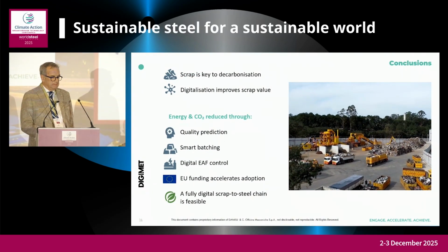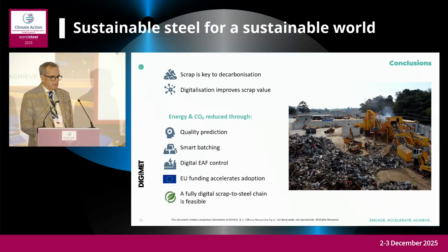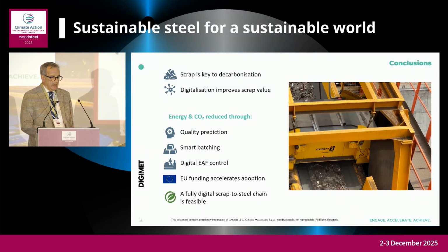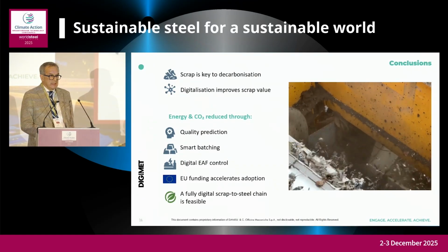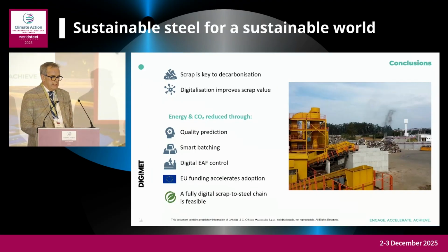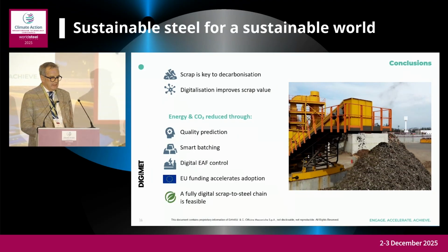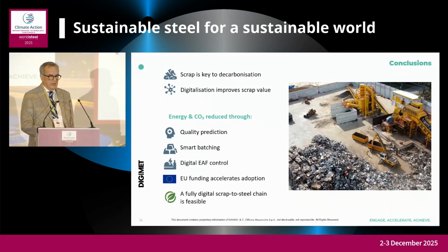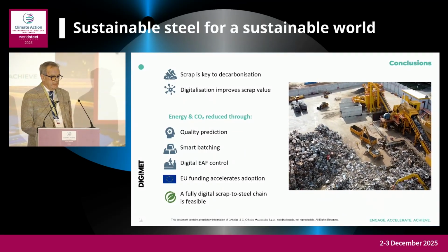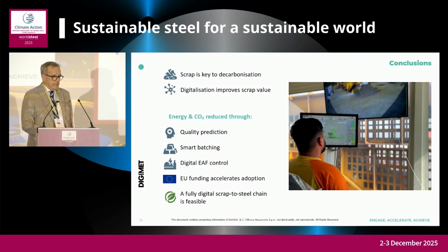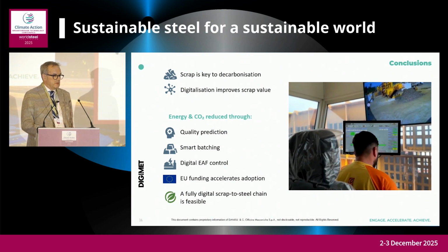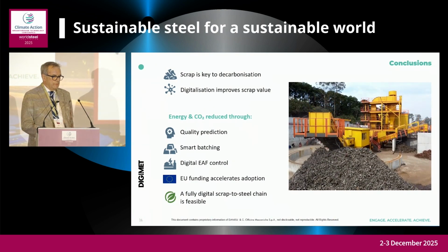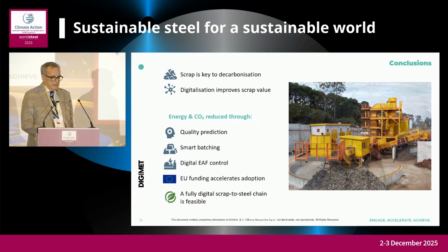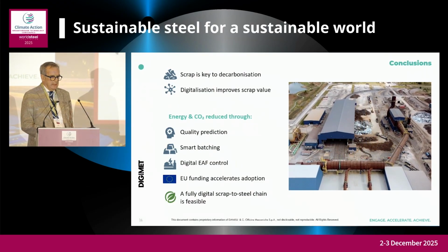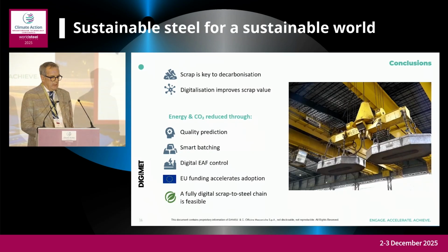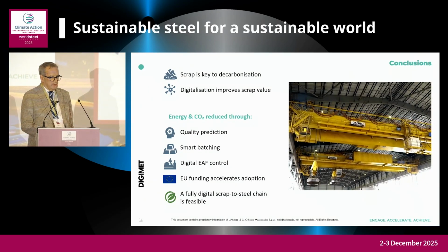Now, let's put the focus on the conclusion. As was mentioned several times in several different presentations, scrap is fundamental in achieving low-carbon steelmaking. We already see that even if we start from rough information today, we are emitting between 0.4 and 0.7, which is 50% or more than 50% less than with the use of the blast oxygen furnace.